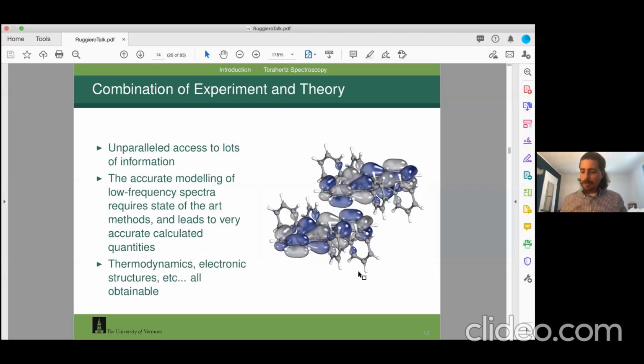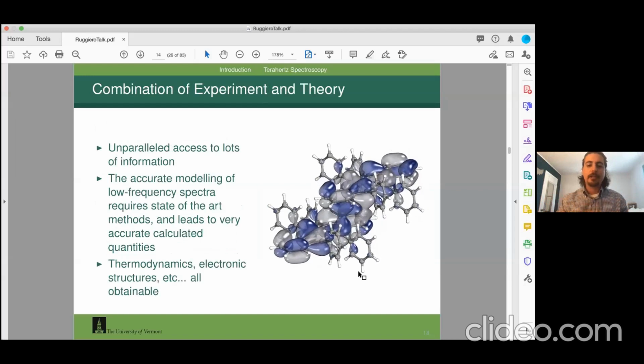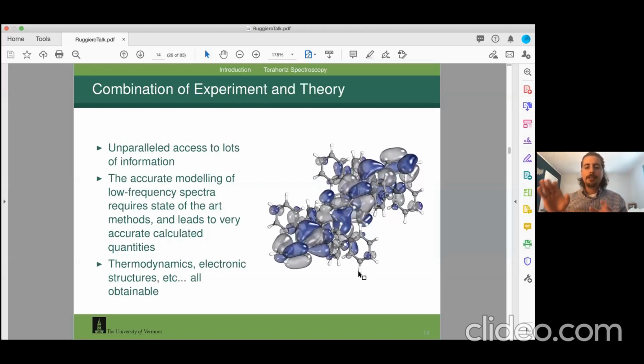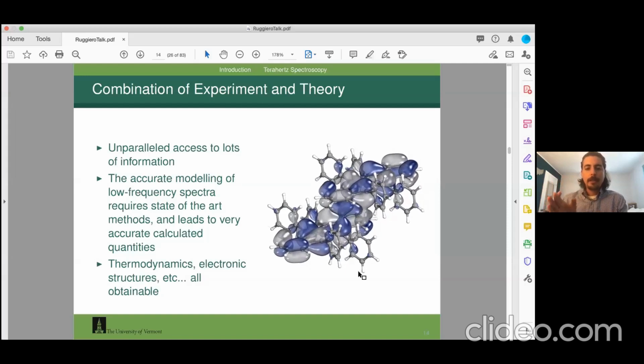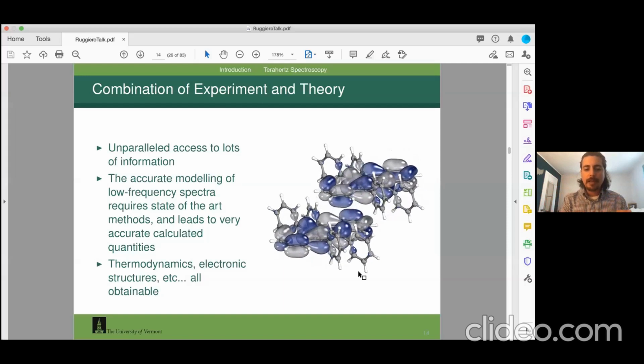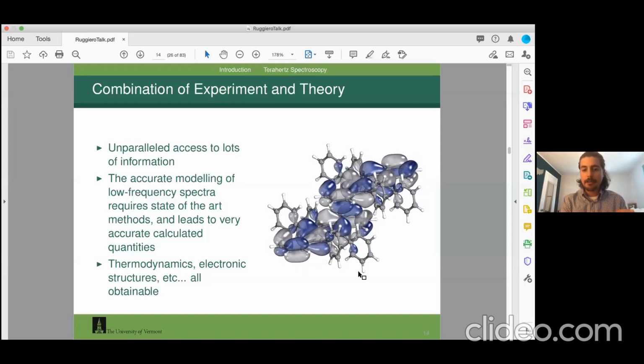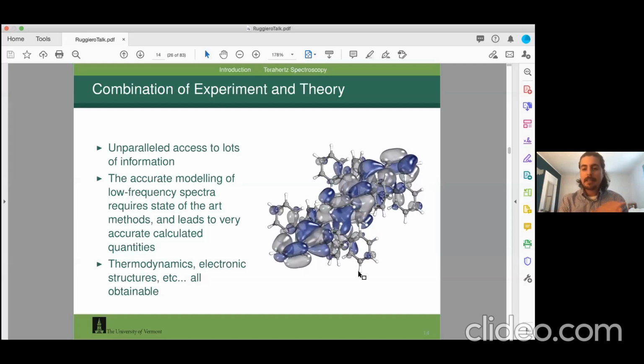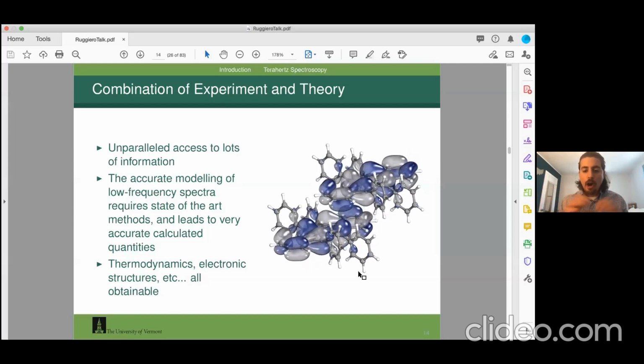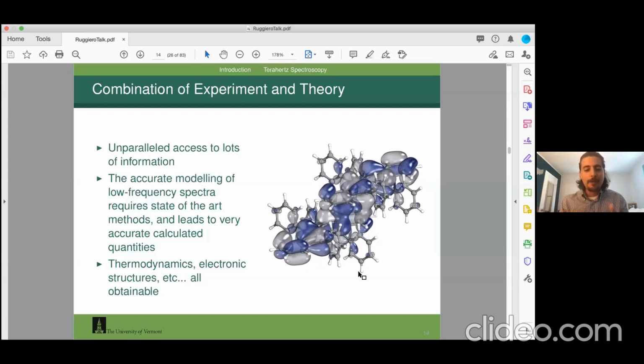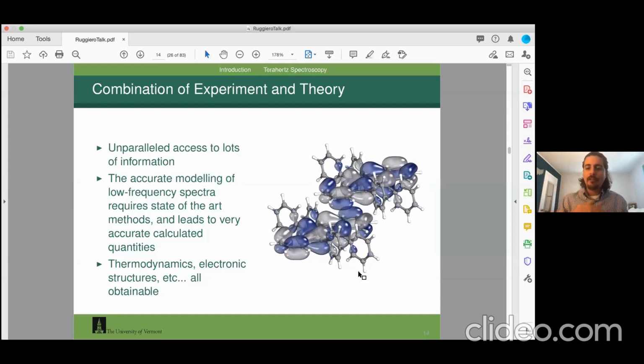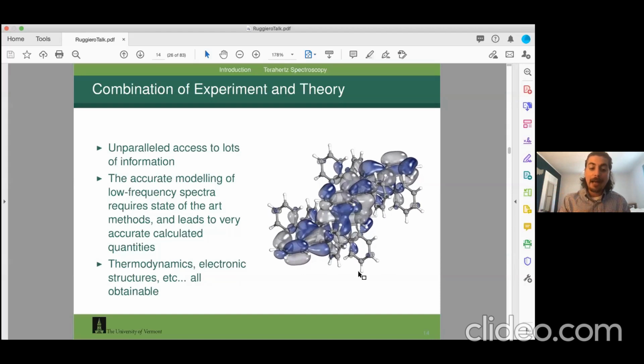Okay, so that was a very long introduction, but what this does for us is really powerful. If we do the experimental spectroscopy, and we get really good agreement between that and our simulated spectral result, that means our simulation is doing an excellent job of capturing all of the forces in our crystal, the weak forces and the strong forces, because if the strong forces are wrong, then the weak forces will also be wrong. One really obvious next step is that if you have all of the vibrations right, meaning you have the terahertz spectrum modeled correctly, then all of your thermodynamics must also be right, because the thermodynamics directly depend on the vibrations.